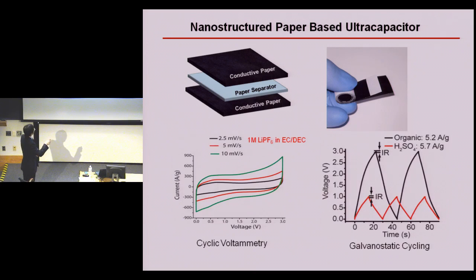Basically, with this kind of device structure, we can do all kinds of tests. But the two common tests we did: we apply current, and we monitor the voltage. It's basically the charging and discharging process. In the other case, we sweep the voltage and measure the current. From either of these two measurements, we can get the most important parameters, either the capacitance, energy density, the resistance of the device, and so on at different frequencies.